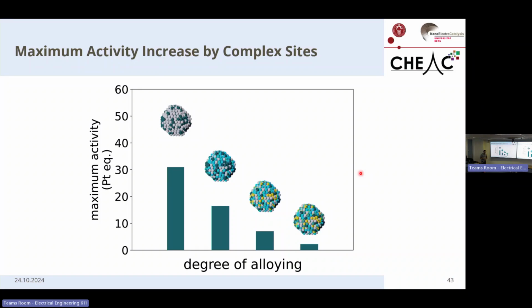And thus we can calculate how much of an activity increase we can get from going up in dimensions and making alloys. A binary alloy can increase the activity relative to platinum by 30-fold if all the binary sites are going to be ideal. But in the case of a high entropy alloy, we can only double the activity, simply because we just have 4% of the surface area devoted to 5-element sites.